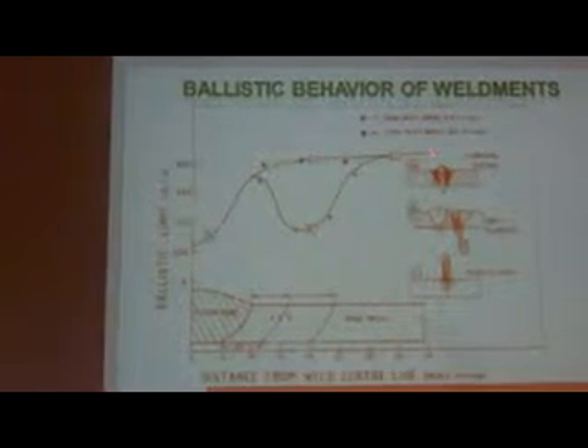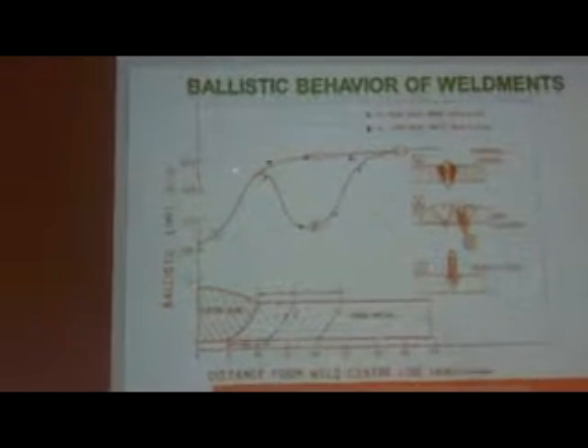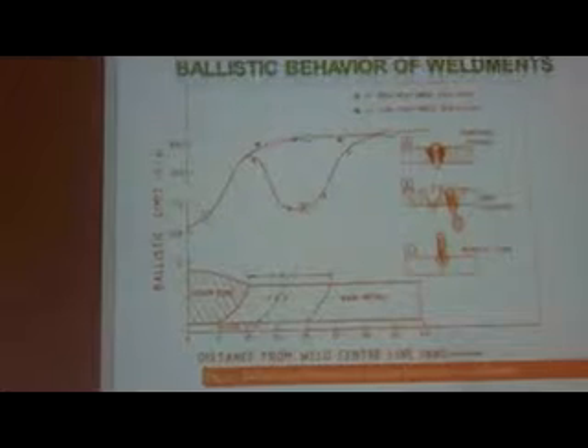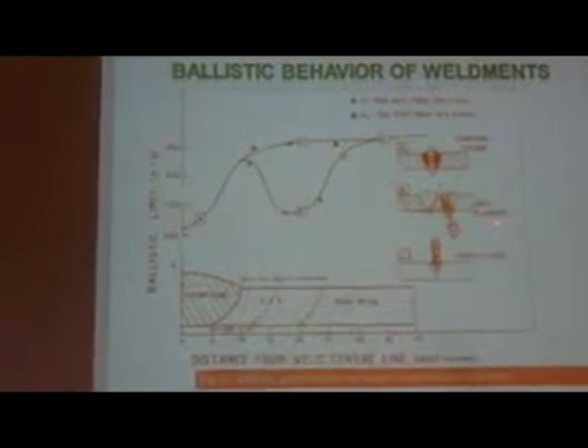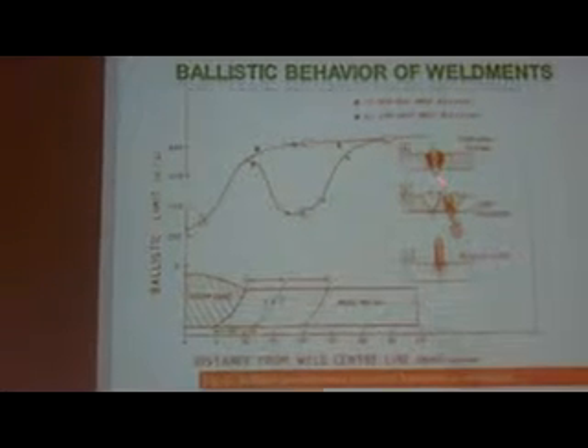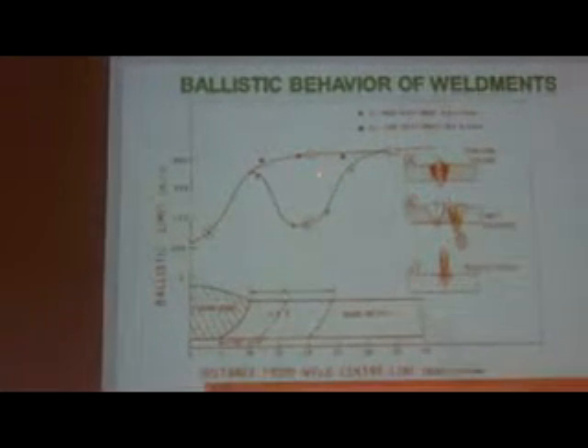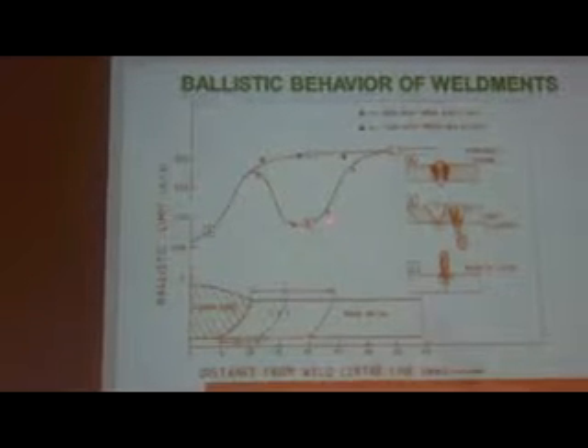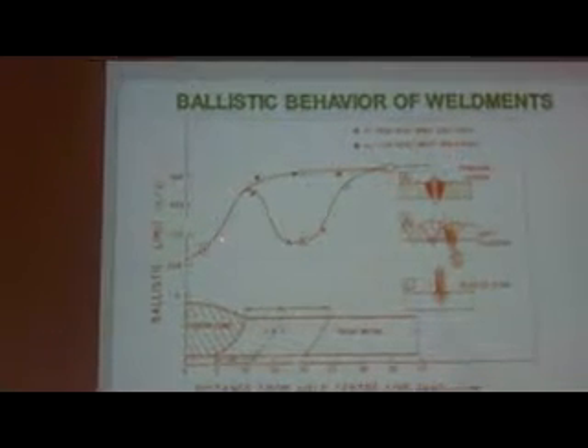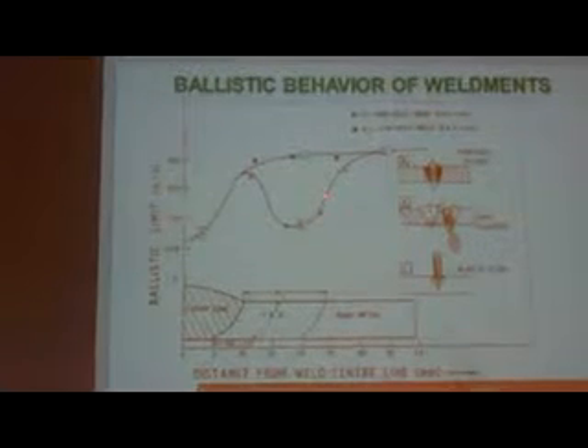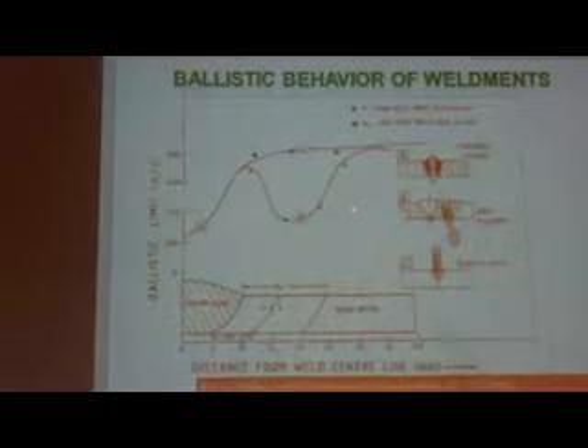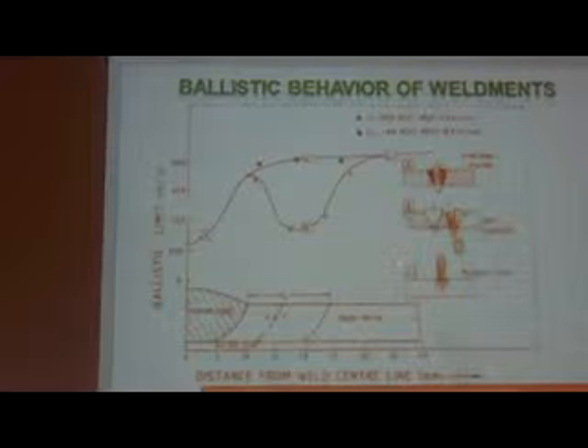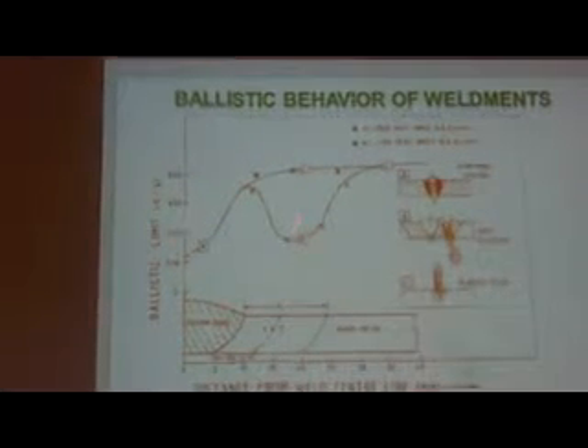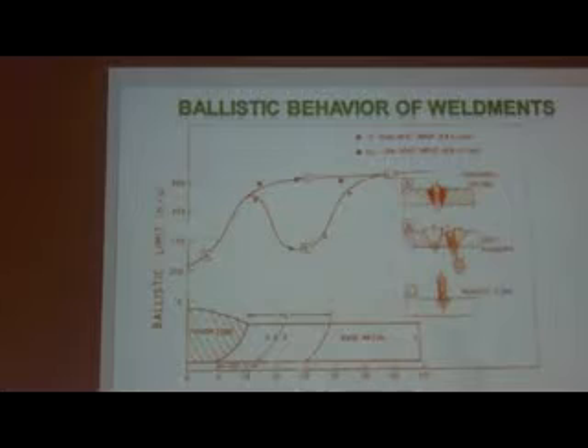And this is the base metal zone. Apart from this region, it is the unaffected base metal, which also offers high penetration resistance, that is called bullet shattering. And in location B, we have a very low hardness profile, which is again compared with your weld metal zone, which offers a higher hardness zone, but it does not work when it is ballistically evaluated. That is the reason this region and region B completely allow the bullet to pass through.